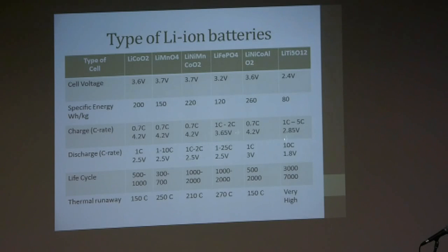And for some reason they reach that thermal runaway temperature, then the internal chemical reaction actually makes them go even hotter. After that, it's the point of no return, and the chemical process generates more heat, and more heat gets that chemical reaction going even more, and you get the situation which you just saw in that little video. So the one with the highest runaway temperature will be one of the safest.